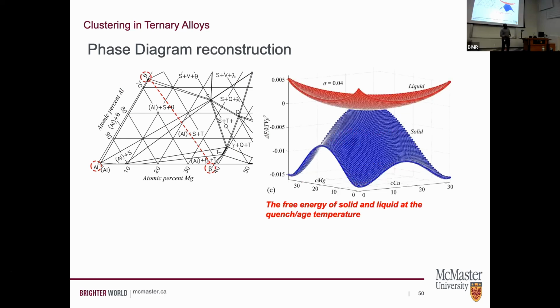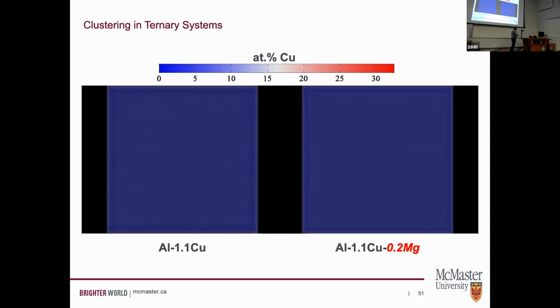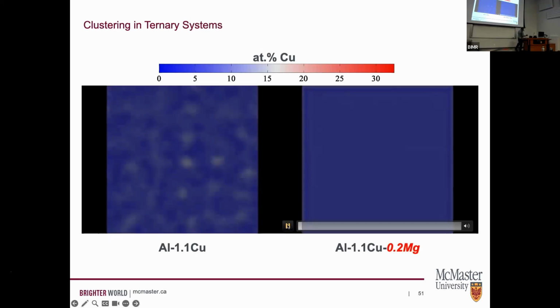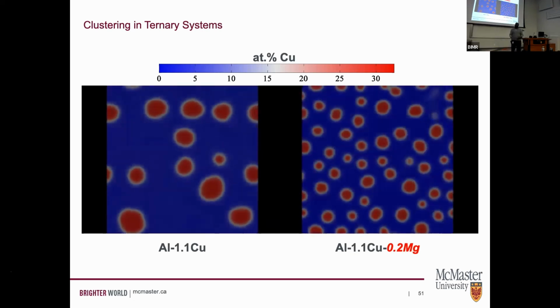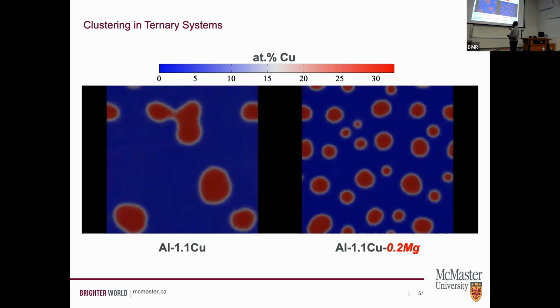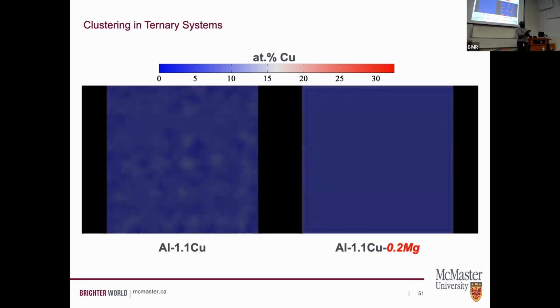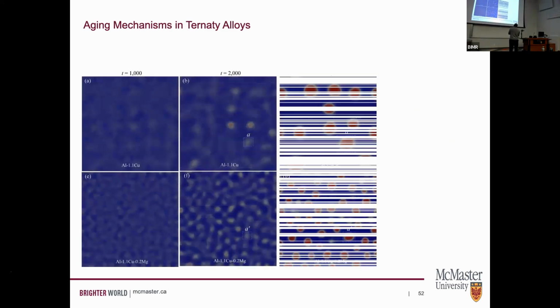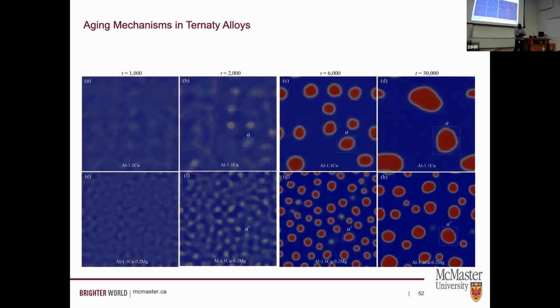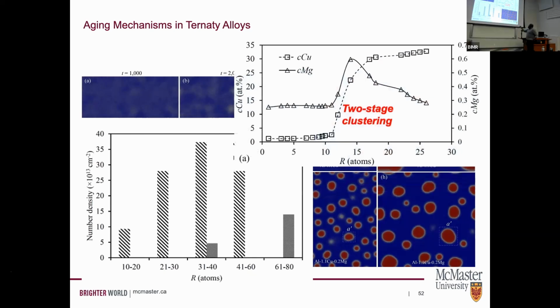We could also play this game with ternary alloys. And the one thing that I want to point out in ternary alloys is interesting. If I take an aluminum copper alloy and an aluminum copper magnesium alloy, it turns out that just by adding that additional alloying element, I get different solute behavior, or different clustering behavior and statistics as well. And so can we explain what's going on here with the addition of a secondary alloying element? Here our explanation was that we're going through a two-stage process. Initially, when our structure is highly distorted, almost liquid-like, both solutes tend to be attracted to the dislocations. But then once the critical radius is reached, one of the solute components, after having stabilized that initial cluster, decides to leave because it's no longer the equilibrium or the preferred place for it.